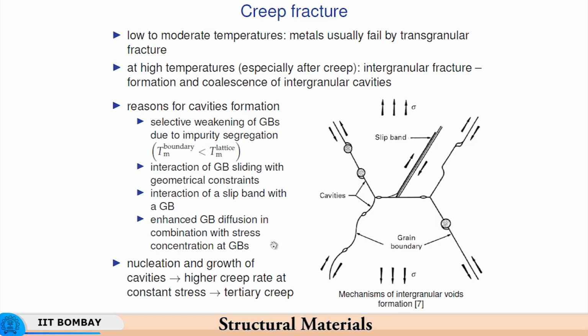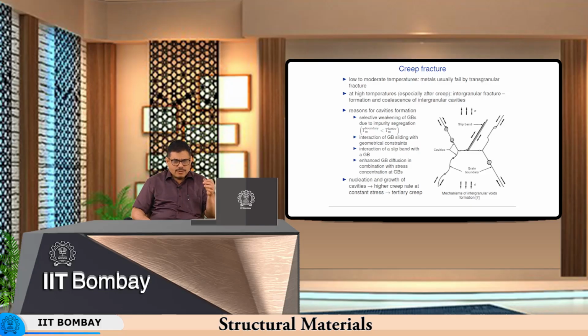Enhanced grain boundary diffusion in combination with stress concentration at grain boundary. So, that is another thing where the diffusivity of the grain boundary can increase in the presence of stress concentration. This stress concentration can come from the presence of, let us say, a scratch, a crack, or any potential inhomogeneity. It could be a significant change in cross section, and that results in increased grain boundary diffusion. And so, basically the structural changes take place at very rapid rates because of the changes in the grain boundary structure or grain boundary profile, the nature of the grain boundary. In one case, the grain boundary becomes weaker, and as long as the impurities do not melt, the grain boundary sliding will be that much more severe, and the diffusion has to accommodate that severe grain boundary sliding.